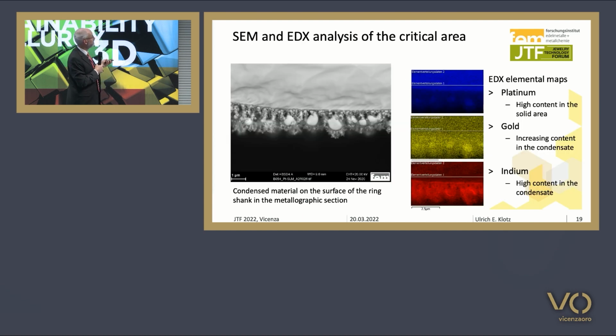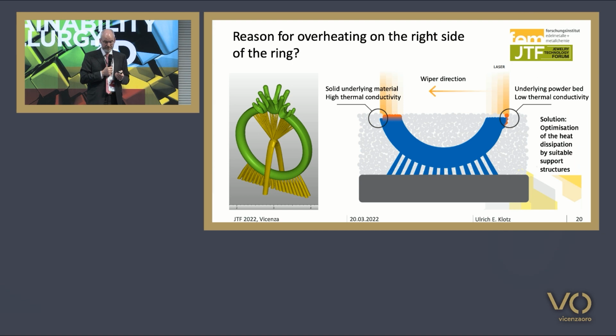This is the condensate in detail, how it looks. This is an elemental map, showing the distribution of platinum, gold, and indium. So all elements are present in this condensate. It's clear that it's coming from the alloy, and especially the indium, which has a very low melting point, is concentrated. So this again confirms the overheating of this area.